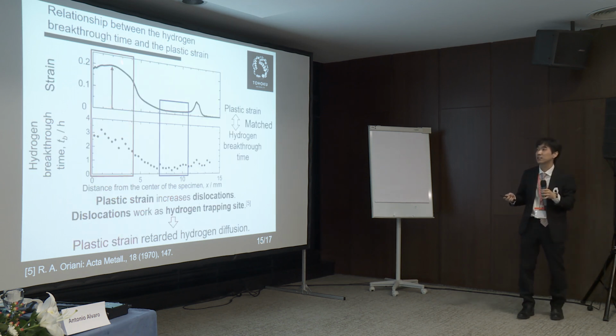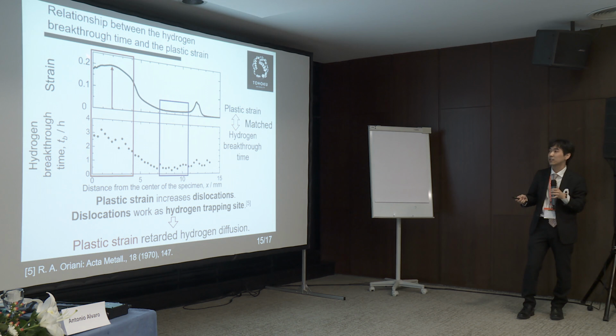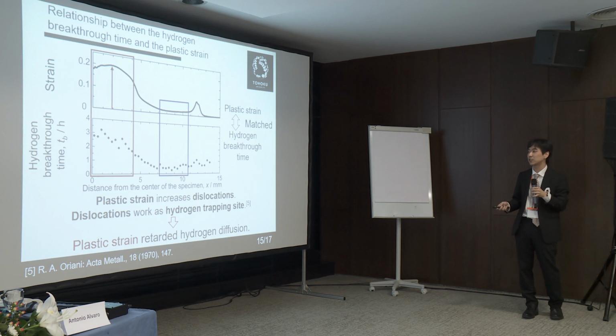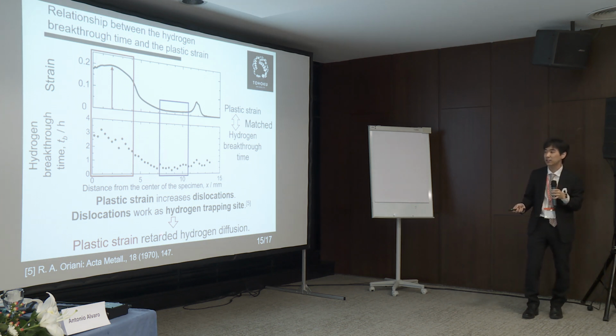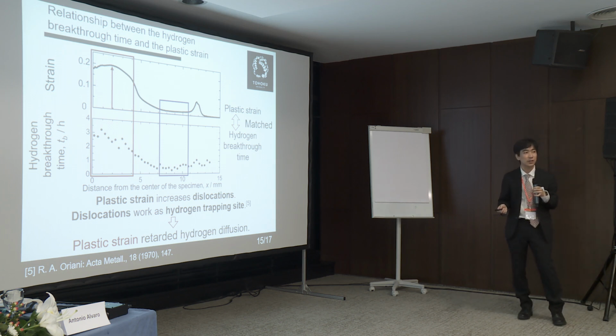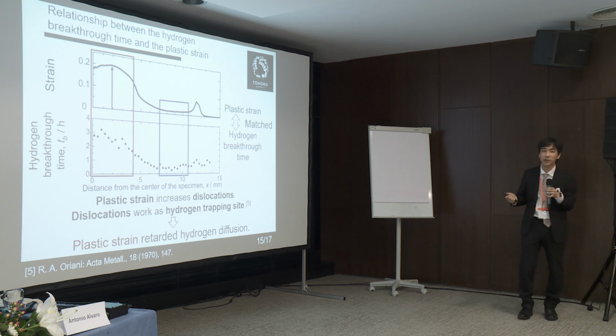And this slide shows the relationship between the hydrogen breakthrough time and the plastic strain. The distribution of the plastic strain and the distribution of the hydrogen breakthrough time corresponded. Plastic strain increases dislocations. It was originally reported that dislocations work as hydrogen trapping sites, so it is considered that plastic strain retards hydrogen diffusion. These results support this fact. So we can conclude that plastic strain has a big effect on hydrogen diffusion and hydrogen breakthrough time.